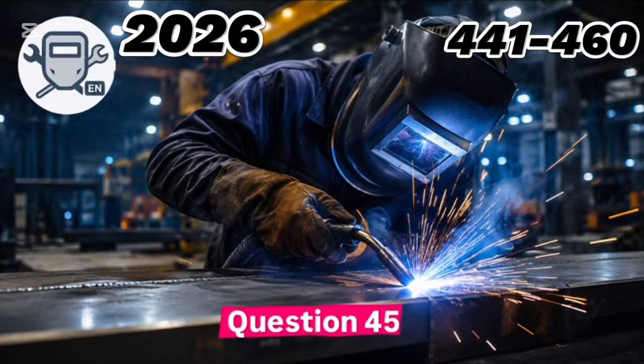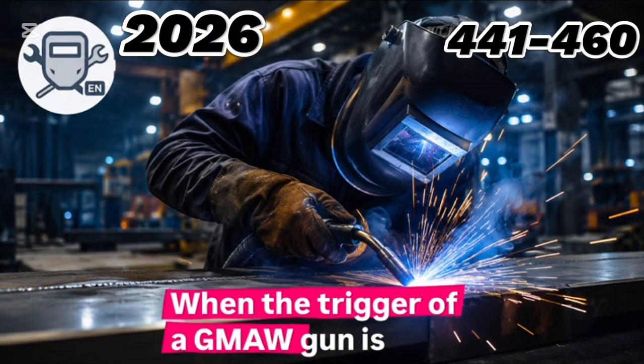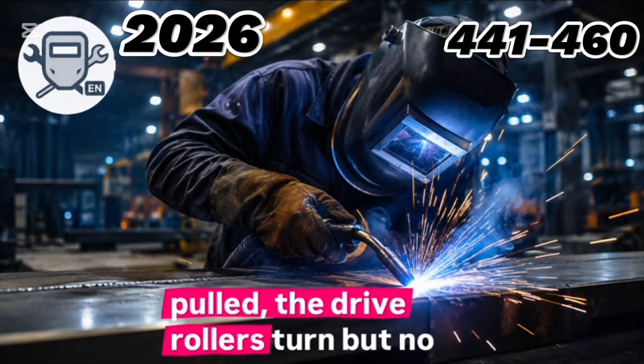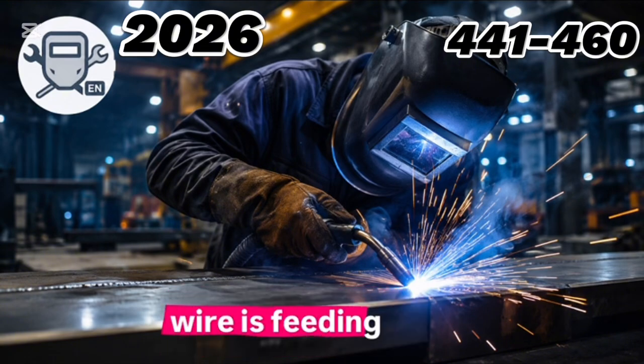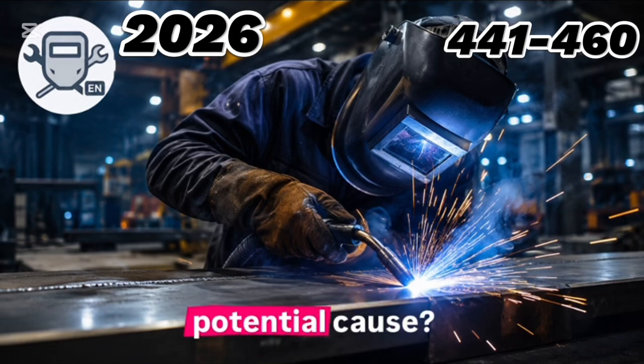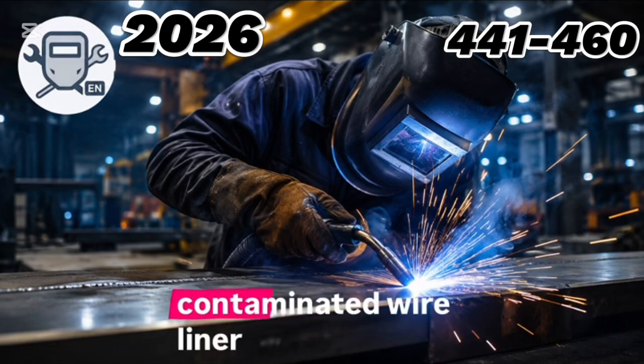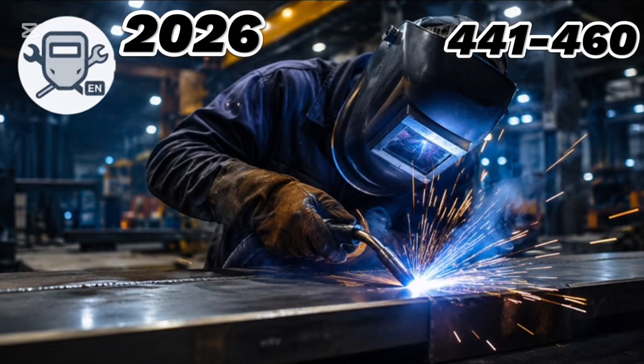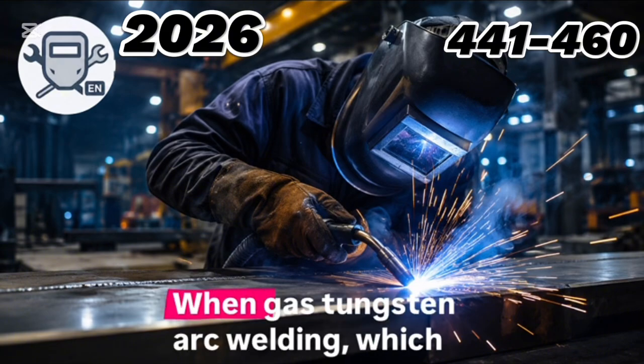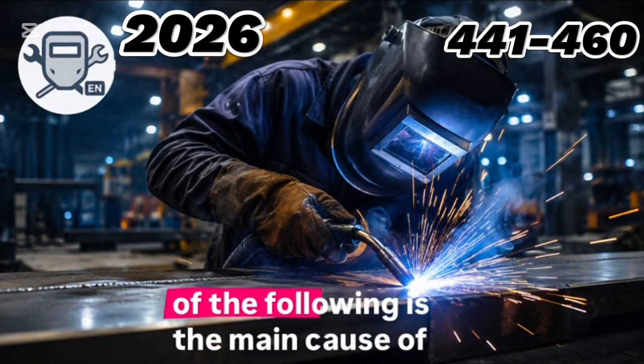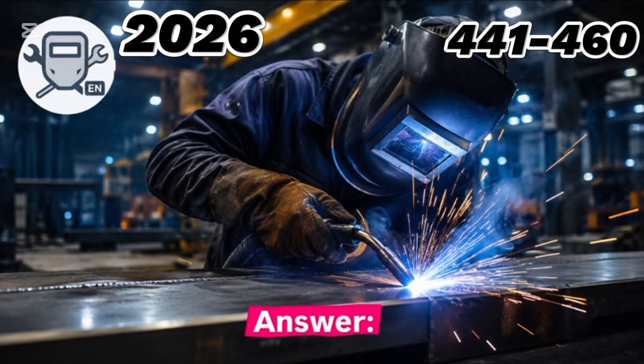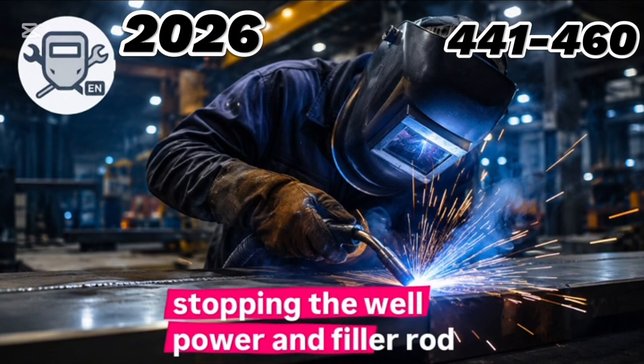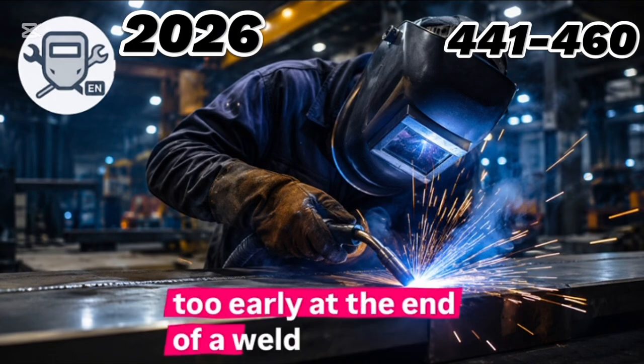Question 45. When the trigger of a GMAW gun is pulled, the drive rollers turn but no wire is feeding. Which of the following is a potential cause? Answer: contaminated wire liner. Question 46. When gas tungsten arc welding, which of the following is the main cause of craters? Answer: stopping the weld power and filler rod too early at the end of a weld.